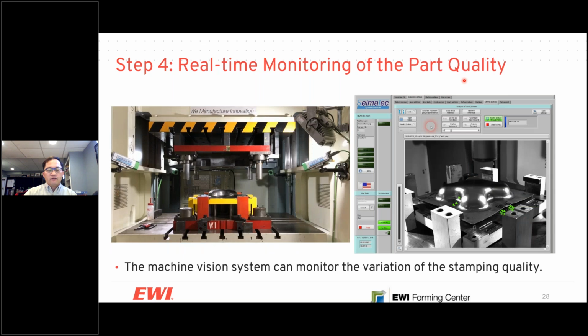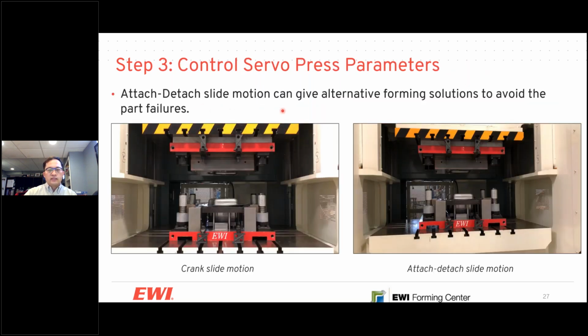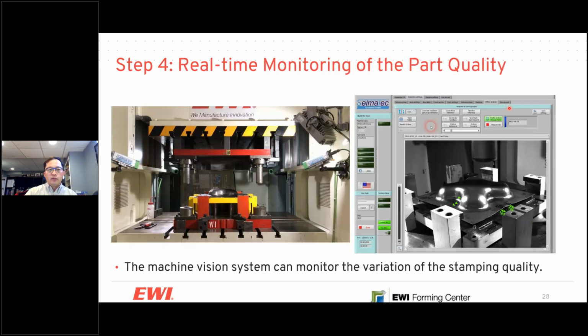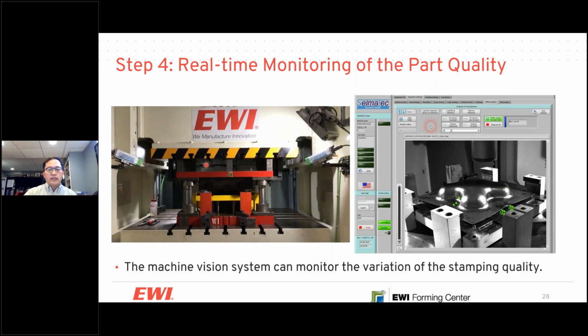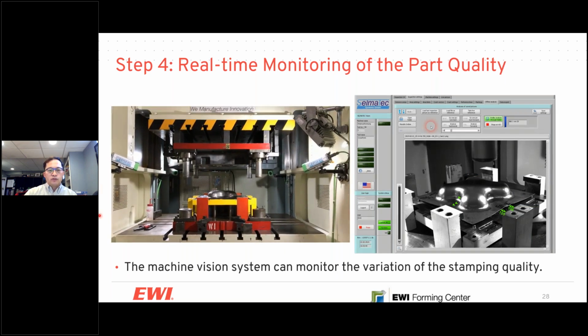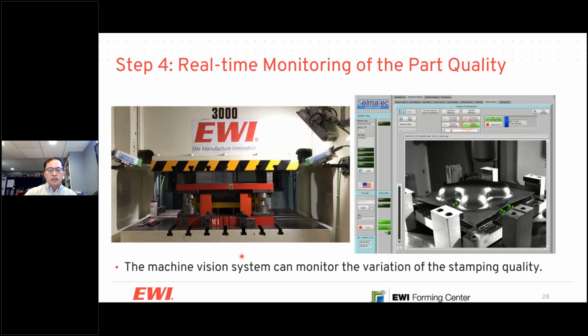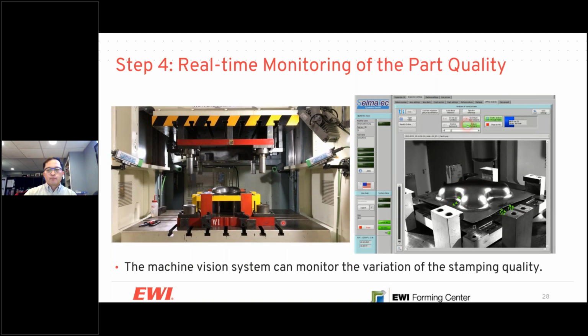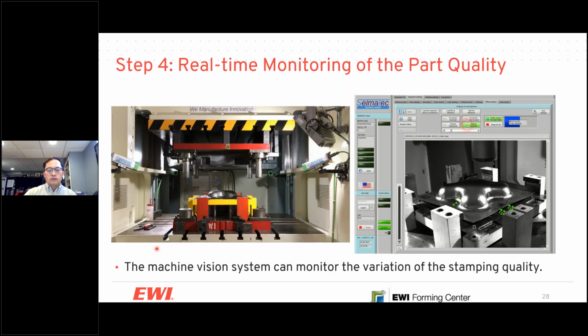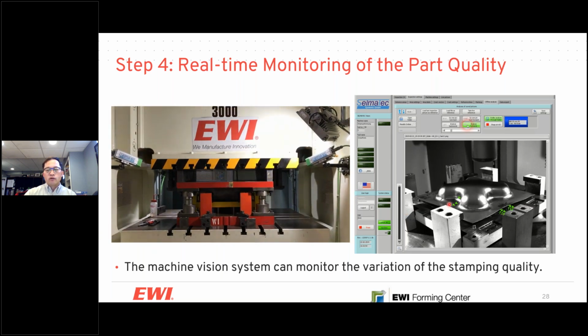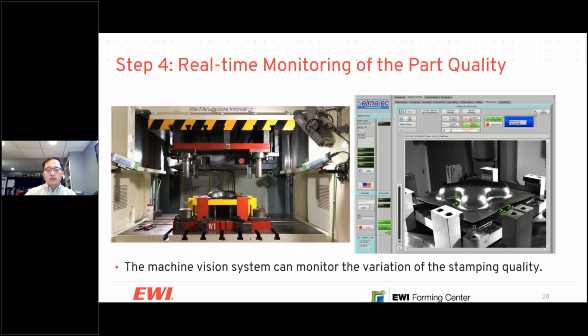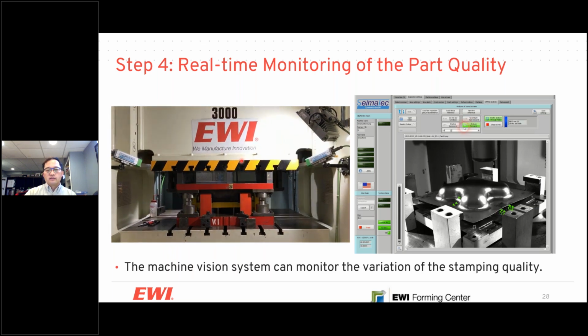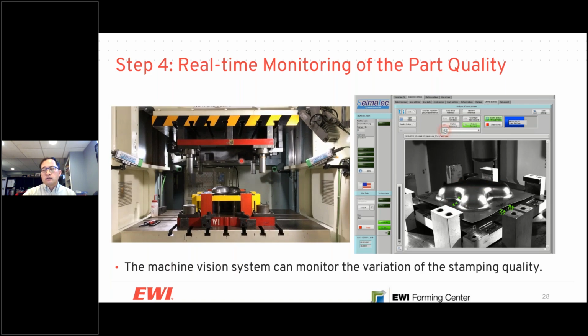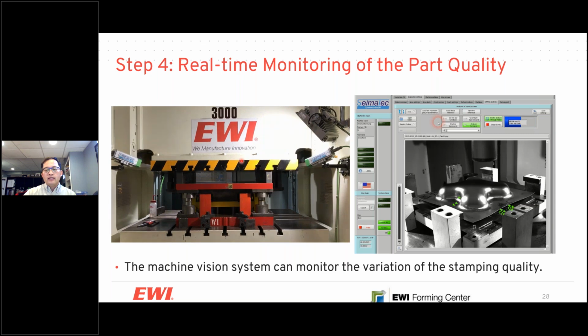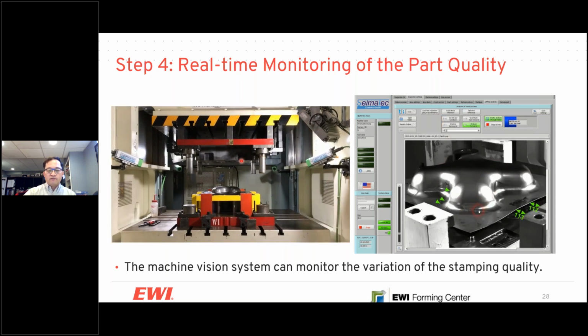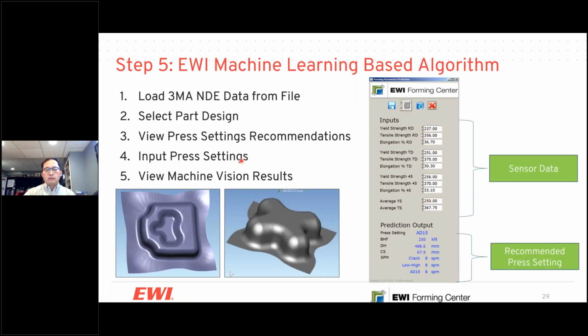From the simulation side, we define the slide motion on the servo press. We can implement that servo press motion, and then the part is measured with the camera system. We have a system that not only records the images but also measures material drawing and cracking on the part during the stamping process. With all the data, it gives us statistical data: what the scrap rate is, as well as how much the variation of the blank edges, the flange edges, will change, which is influenced by lubrication as well as the material properties.